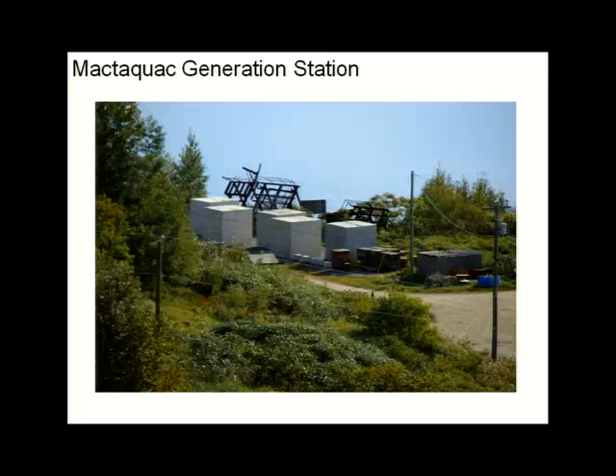There's a control block, so no mitigation options at all. Then there's a 30, a 40, and a 50% fly ash replacement in each one of 3 additional blocks. There's also a 5th block that has a 50% fly ash replacement that's from a deposit of fly ash that's been specifically reserved for this dam.